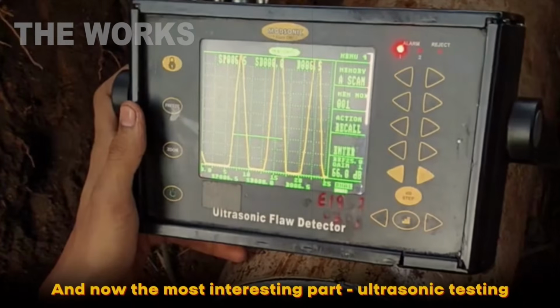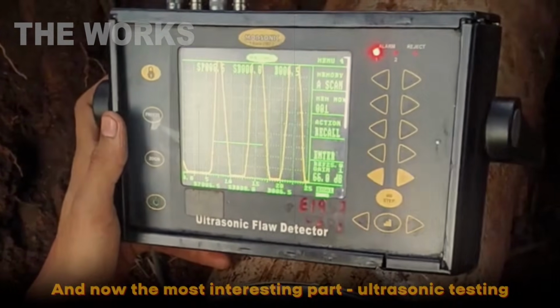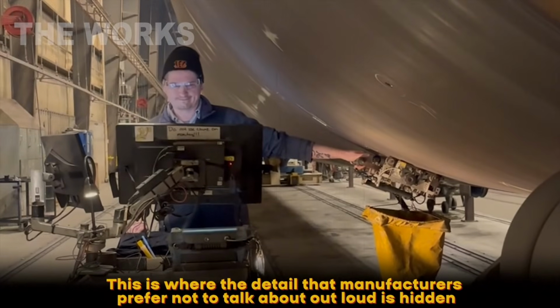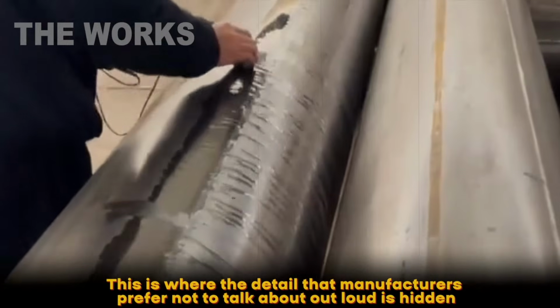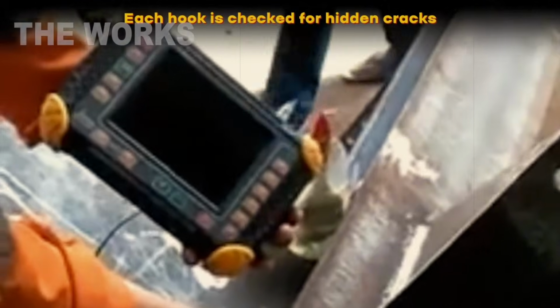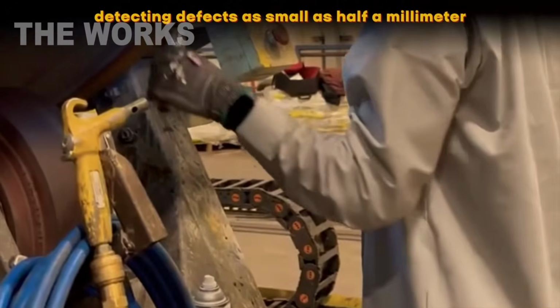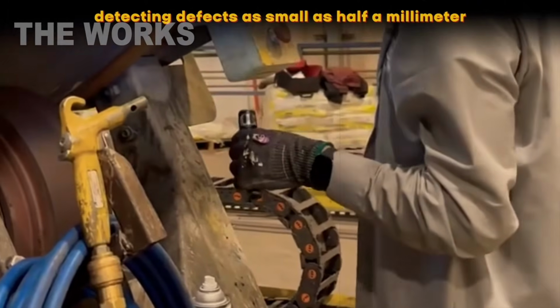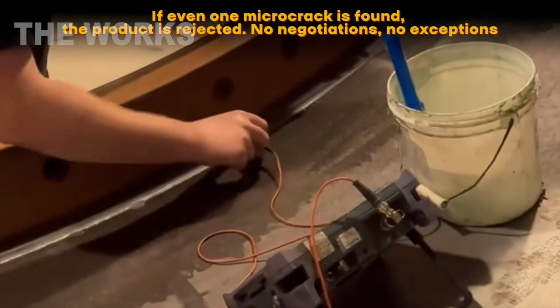Now here's where it gets really interesting: ultrasonic testing. This is where manufacturers hide a detail they'd rather not talk about. Every hook gets checked for hidden cracks. Sensors scan the metal with a 5 MHz wave, detecting defects as small as half a millimeter. If even one microcrack shows up, the part gets scrapped.